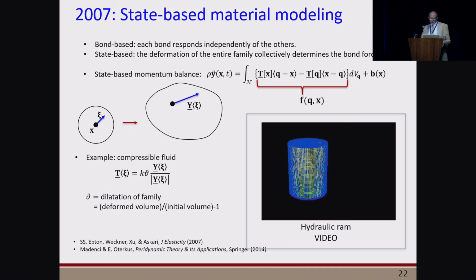In 2007, in response to the lack of generality of bond-based materials like the microelastic material I talked about before, we started working on state-based material modeling, which is a more general version. The problem with assuming that each bond responds independently of all the others is that it results in some restrictions on the material properties you can reproduce. Notably, you always get a Poisson ratio of 1/4. So to avoid that, we developed a more general framework for material modeling called state-based rather than bond-based. And the idea is that the bond forces are determined not only by the deformation of the individual bond, but also collectively by the deformation of the entire family.